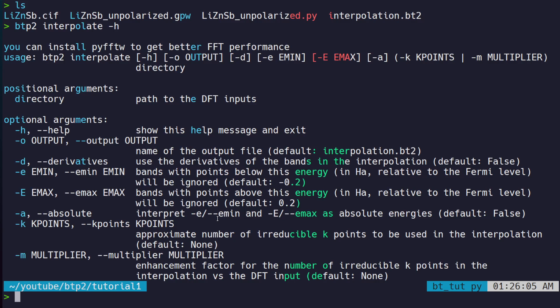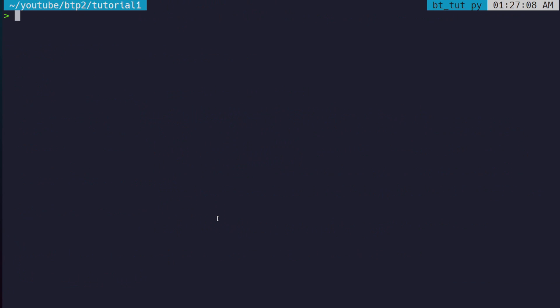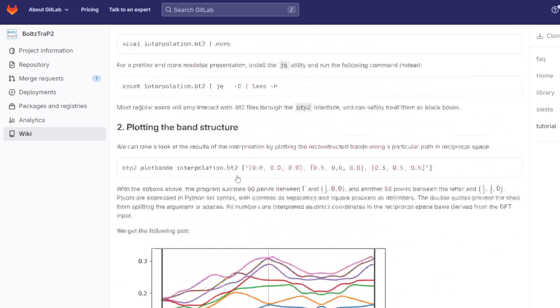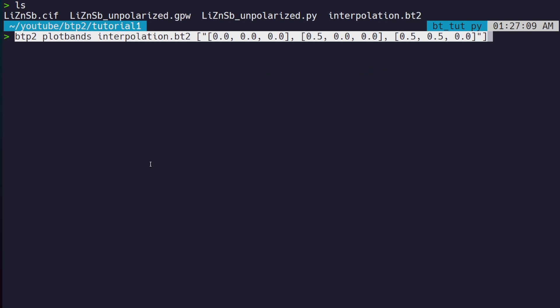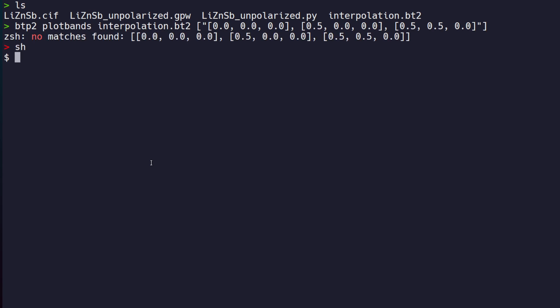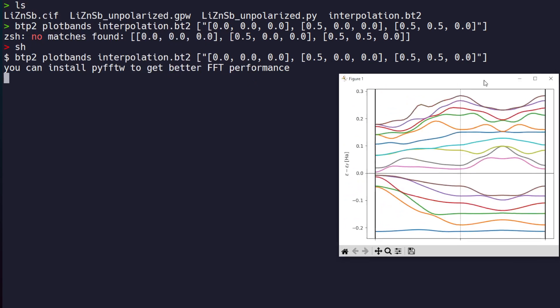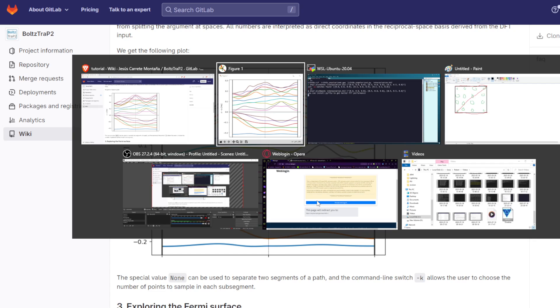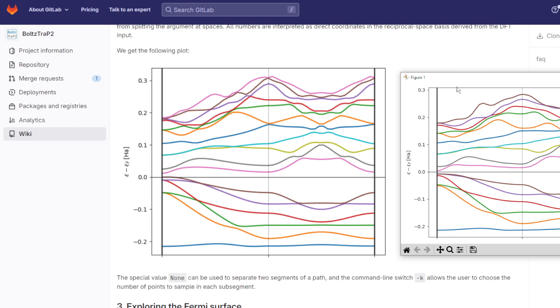It's clear now we can plot our bands to see how they look compared to this system. You can see almost immediately they look really more or less identical. The only difference is that maybe we have a different number of bands included at certain points. At some points they're not separated here, and there seems to be a little bit of a rigid shift of our bands compared to the BoltzTraP2 reference data. This kind of stuff is to be expected when using different DFT codes, so we have relatively good agreement.